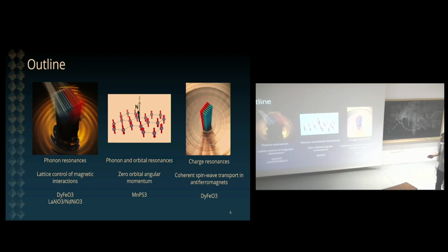In this talk we are going to first discuss the excitation of phonons in our favorite complex oxides. So we will start with a simple example of an insulating material, lanthanum aluminate, and we will see what happens when we excite phonons at resonance and we interrogate structural dynamics. I will try to show you that this resonant phonon excitation brings about a number of rearrangements in the structural properties of the system, notably the excitation of Raman phonons, starting from the excitation of infrared active phonons, and the formation of strain waves that propagate across the material. So both longitudinal and shear strain waves.